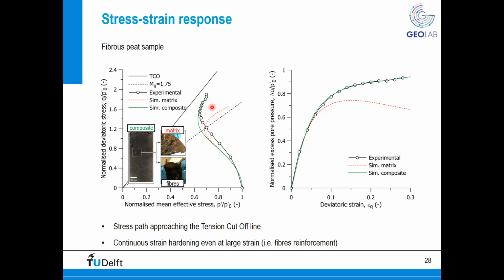So the idea here is just to show you how the behavior of peat could be better captured if we assume that peat is a composite soil. So peat is at least a superposition of a matrix, which is basically characterized by very small fibers, but also by big fibers that provide an additional confinement to the sample. This is the result of a constitutive model that we have developed here in Delft. You see that the matrix, which is the red dashed line, already reached critical state for a friction angle of about 42 degrees. But if you overlap the contribution of the fibers, the overall stress-strain path of our soil composite is much higher.